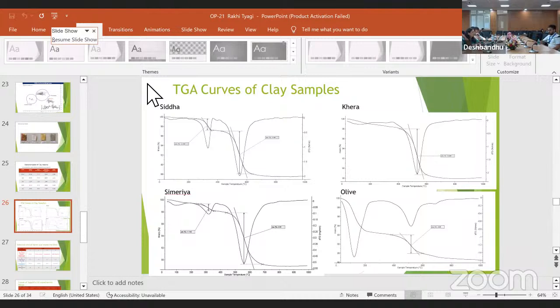As we can see, the TGA curves of Siddha and Simeriya show a peak between 200 and 300 degrees centigrade, which is due to goethite, as we have already seen in the XRF data. These two samples are rich in iron. The last sample, Olive, showed a peak below 200 degrees centigrade, which is characteristic of smectite clay material.